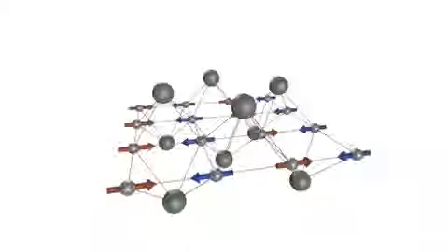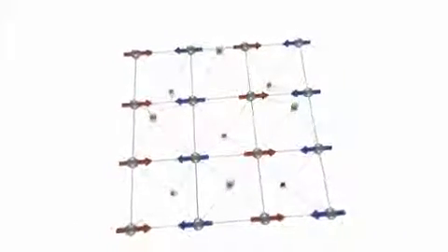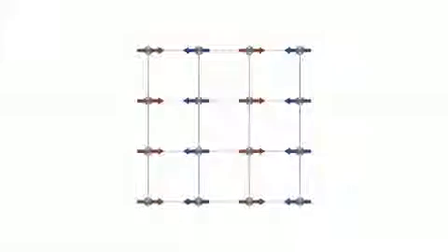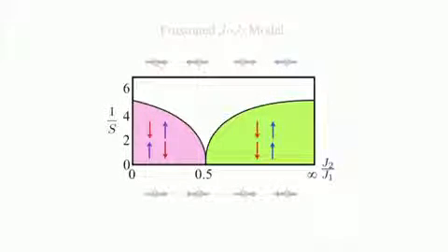For example, spin systems on a square lattice can be frustrated when the nearest neighbor and next nearest neighbor interactions are both antiferromagnetic. The role of frustration has now been discussed in the newly discovered iron-based superconductors. In these materials, iron spins are ordered in a stripe pattern, with moments smaller than 1 Bohr magneton, and this phenomenon could be accounted for by a frustrated J1, J2 model. When J2 is larger than half J1, a collinear antiferromagnetic ground state is stabilized, and the moment is suppressed due to the system's proximity to a magnetic quantum critical point.